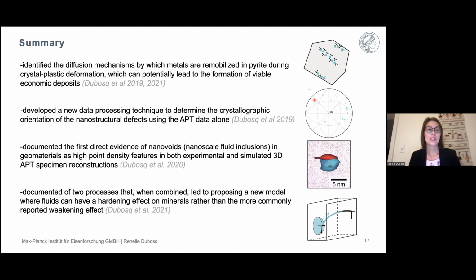So here I just wanted to summarize some of my key findings during my PhD thesis. So I was able to, by applying APT analysis, identify the diffusion mechanisms that lead to metal segregation in crystalloplastically deformed sulfides. So this is very important as it can lead to the formation of viable economic deposits. I was also able to develop a new data processing technique, pushing the limits of APT, to determine the crystallographic orientation of the nanostructural defects using the APT data alone.